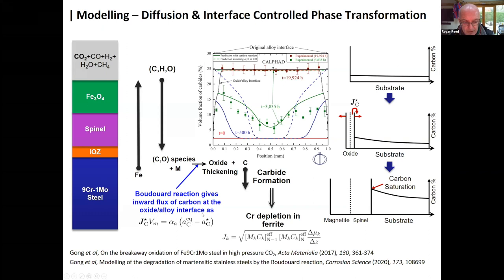And that boundary condition I didn't really know about until this project, but you can see one needs to have this proportionality constant, which is known as the Robin coefficient, which of course is also temperature dependent. And this boundary condition here is consistent with chemical reaction control at a moving interface. So you can see here that as we progress through in time, the net carbon content at the interface is increasing.